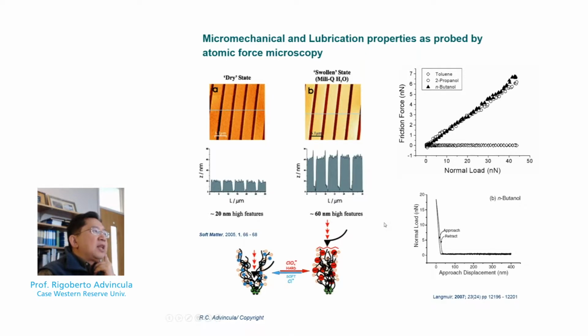Here is one interesting example which shows that the micromechanical and lubrication properties of a surface can be changed as well by the condition as well as the patterning on a surface. So what we have here is basically a polymer in which we have different charge densities and regimes. Depending on the type of solvent, it will have a variety of friction force properties on a surface. Dry state or swollen state, for example, can cause changes in the height of these polymer brushes and hence affect some of its wetting behavior.